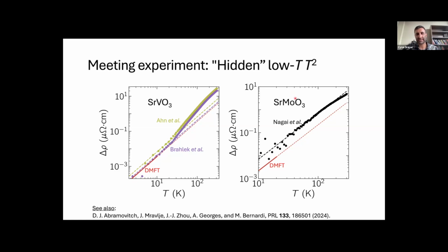In strontium molybdate, it's a little bit harder to see. The measurements are more challenging in this regime. But you can see that the points are starting to fall below the line and are consistent with our, again, lower temperature, lower A coefficient T-squared regime. I think in this Brahlek paper, this was called a hidden low temperature Fermi-liquid T-squared regime, and that is in agreement with our DMFT calculations. So from these calculations, we can attribute this low T-squared to electron-electron, Fermi-liquid scattering.